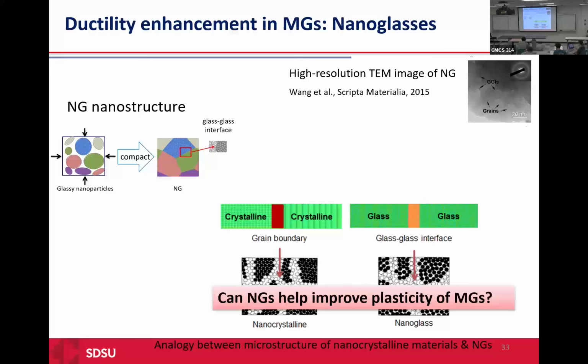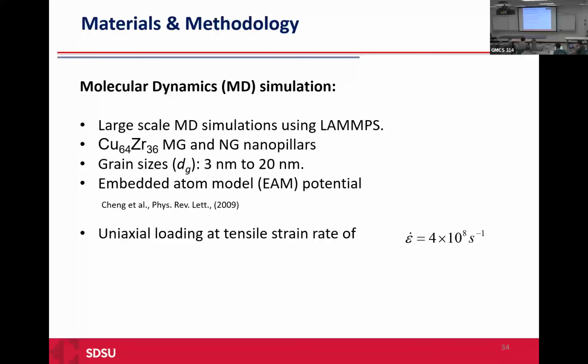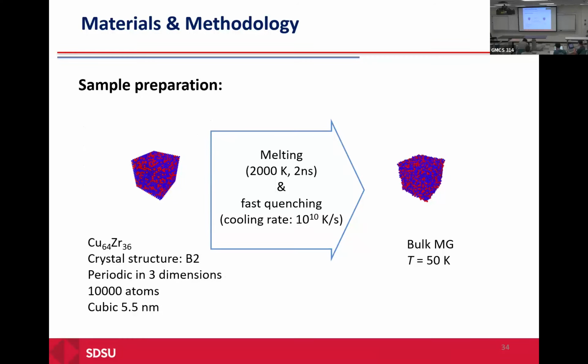Now we want to see if this nanoglass microstructure can really improve the plasticity of metallic glass material. We use molecular simulation, and the structure that we have chosen was copper zirconium, nanopillar copper zirconium for different grain sizes. We started with crystalline copper zirconium, then melted it to 2000 Kelvin, and then fast quenched with the rate of 10¹⁰. Of course, the cooling rate is much higher than the one in the experiment, but it was the one that we could afford for those types of samples.